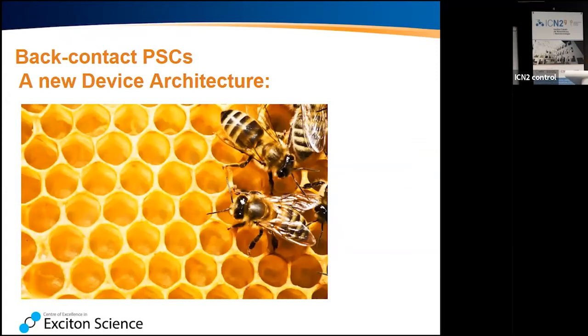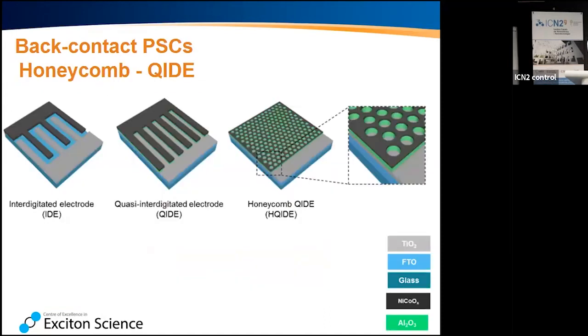What we have now is a back contact. We changed the design again. Rather than having these fingers that are very sensitive, you need to think about their aspect ratio. They are about a micron wide, but millimeters, thousands of microns, long. So if there's a defect somewhere, you cut off the entire finger.